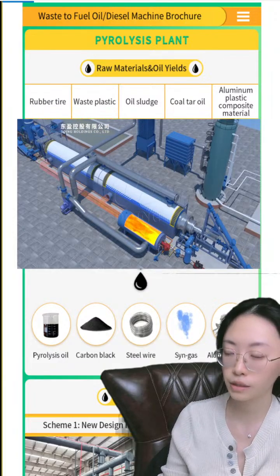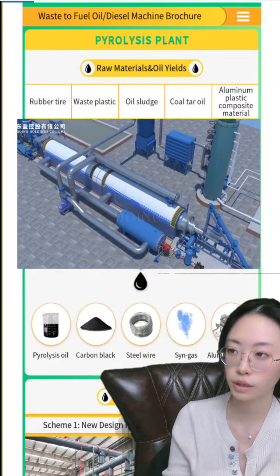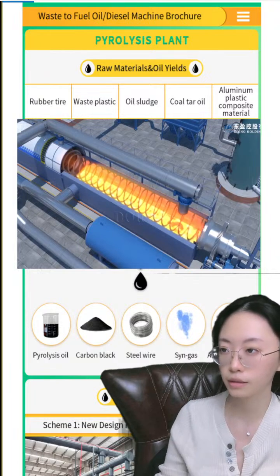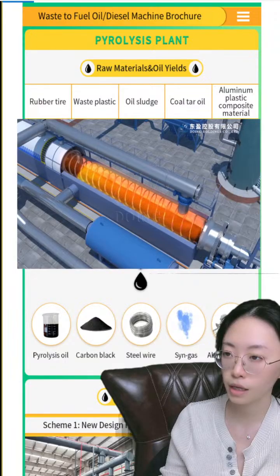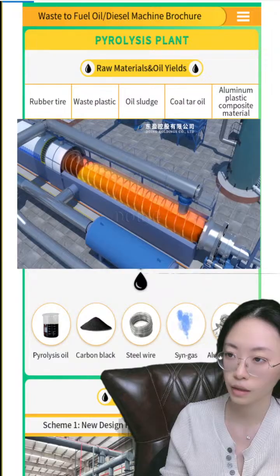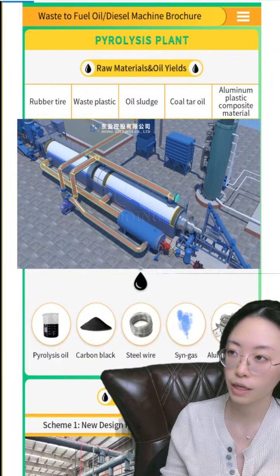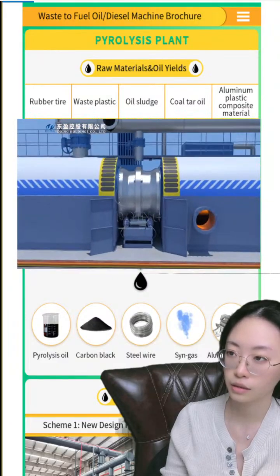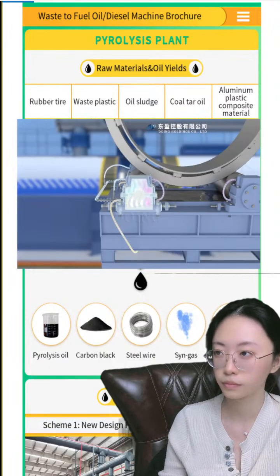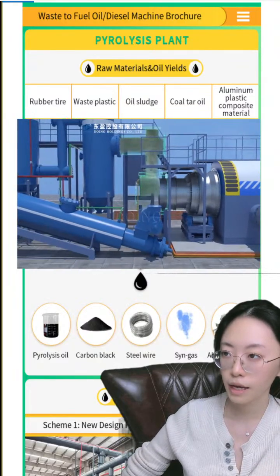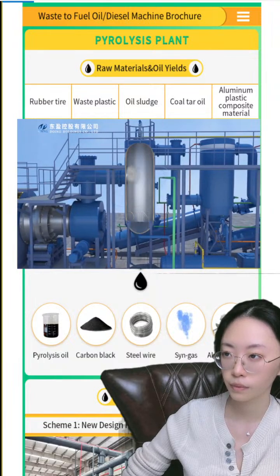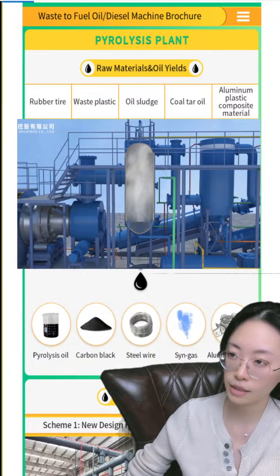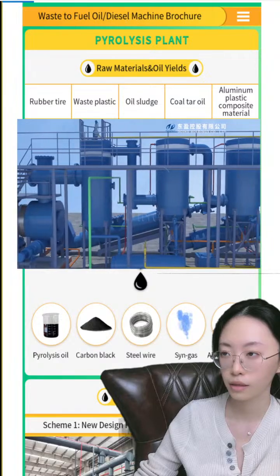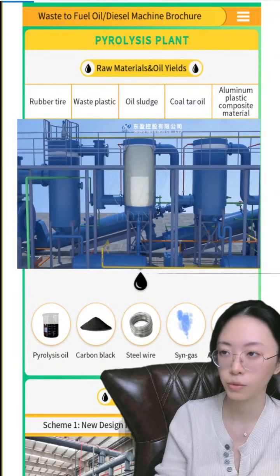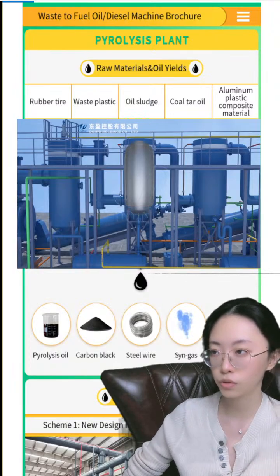And here is the pyrolysis step. We will use the hot burner to heat the reactor. This is an indirect heating way, in order to prolong the service life of the reactor. Inside, the rubber powder is at a temperature of 350 to 380 without oxygen. And then the gas will come out to the condensation system. The first is a buffer tank, which will slow down the speed of the gas and settle down impurities. And then here is the condensation buffer tank, which has a water cover, will cool down the gas into oil, and also at the same time slow down the speed.